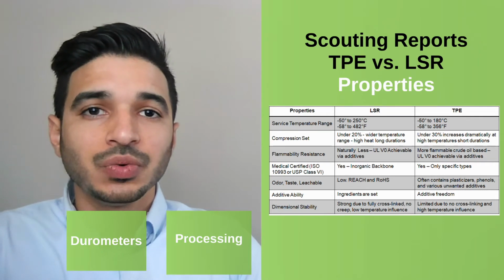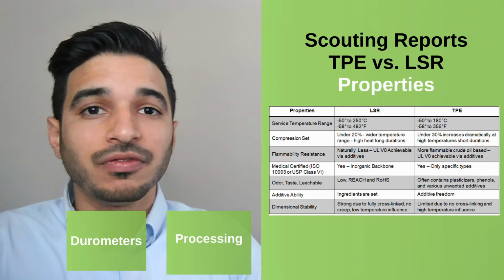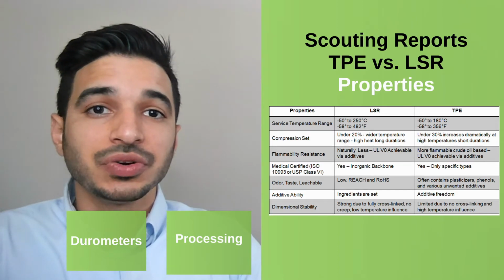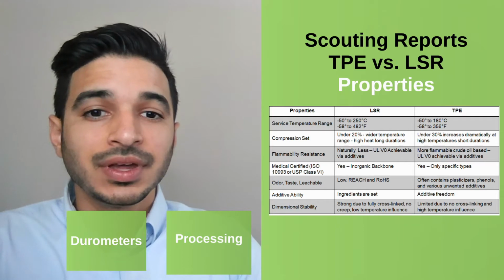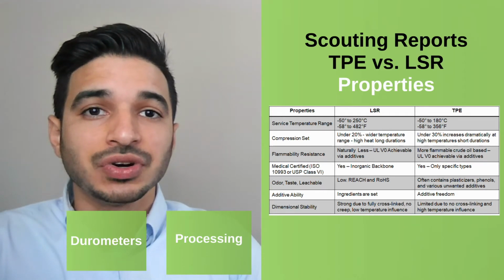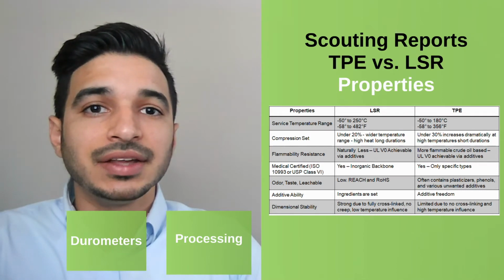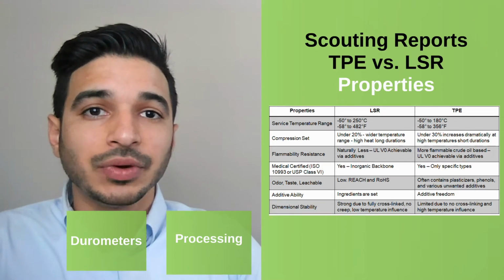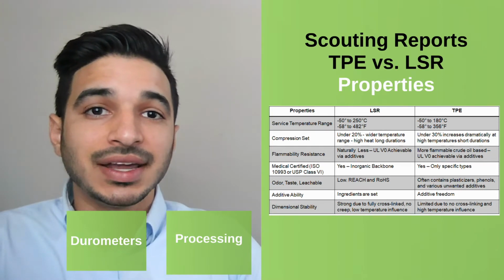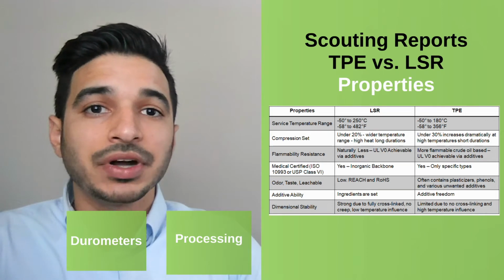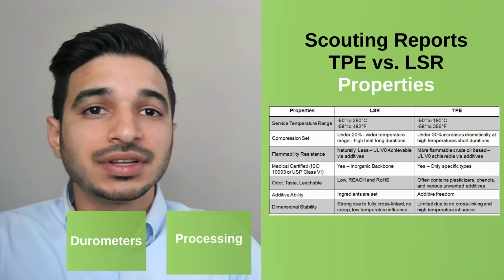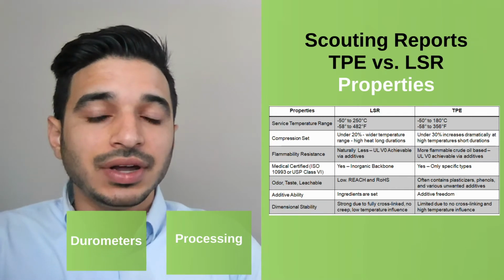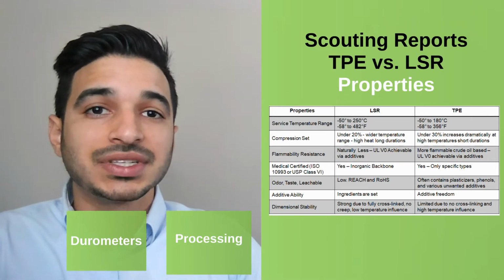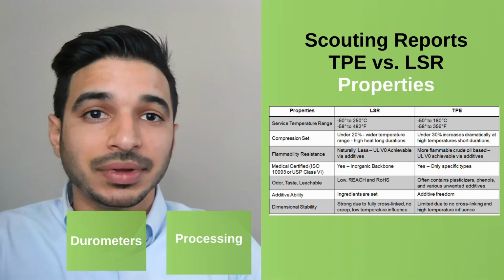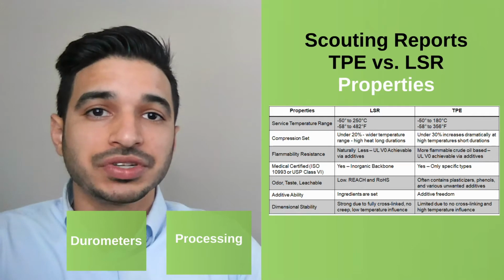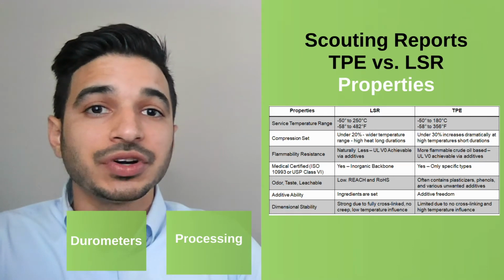When it comes to compression set, which gives you an understanding of how well the material will perform in a sealing application, especially during high heat or harsh conditions, the material is tested by compressing it to a certain thickness or a certain percentage and is then put in an oven or some other accelerated environment. It's then taken out, released, and measured to see how much it returned to its original state. So for this, the lower the percentage, the better. For LSR, it typically can go under 20%, and it can withstand the harsh heat applications and maintain that under 20% quite well. Certain specialty grades can even go under 10%.